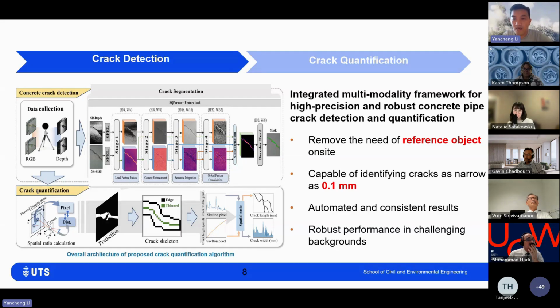The reason we introduced this is that crack detection is normally easy using an RGB image, but your measurement of crack length and crack width is in pixels. We have to convert this pixel measurement into physical measurement. Typically people put a reference object beside the crack, which is not doable if you want to work very quickly. Introducing this depth map removes the need for a reference object on site. We also introduce a super resolution technique in this algorithm, with the aim to really zoom into the detail of the pixels, and we are able to detect cracks as narrow as 0.1, even less than 0.1 millimeter in width.